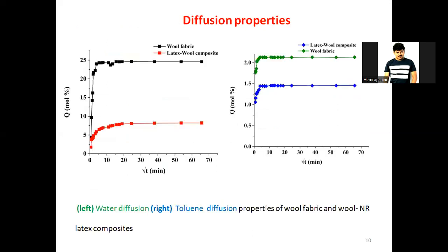Now these are the diffusion properties. On the left side you can see water diffusion, and on the right side toluene diffusion. In water diffusion, the natural rubber latex wool composite showed very little absorption of water, while wool fabric showed high water absorption, because wool is hydrophilic in nature and absorbs a lot of moisture. In toluene diffusion, here also the latex wool composite showed minimum diffusion compared to wool fabric. But in wool fabric there are pores, so the absorbency is higher.